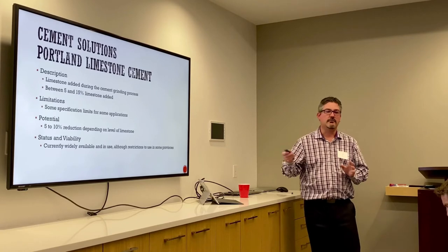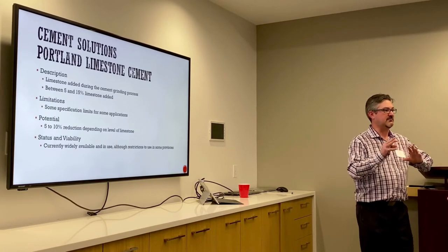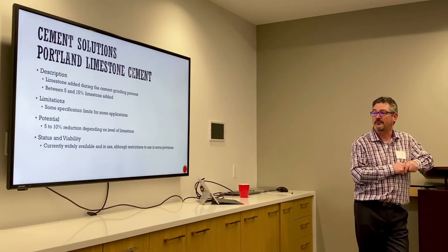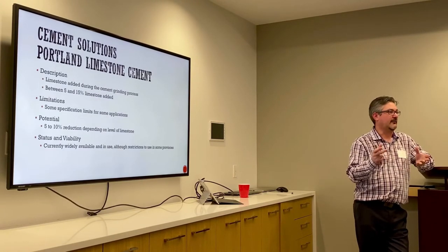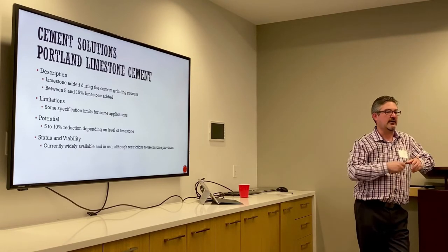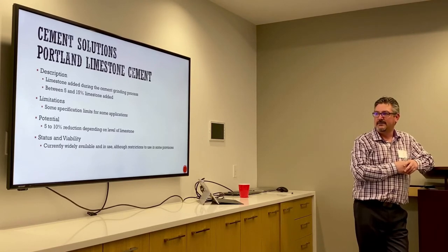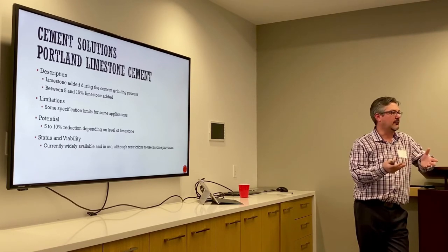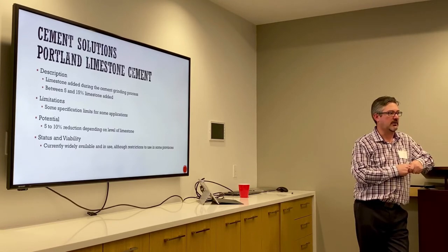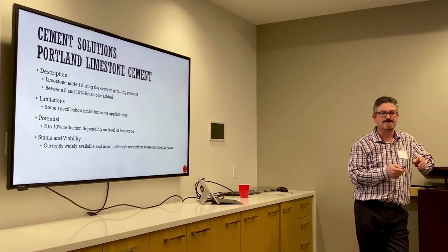So what's the potential for CO2 reduction here? Between 5 and 10%, depending on the level of limestone that's actually used in the cement. And as far as the status and viability goes, for each of these 4 points, I'll be going through all of the different items here and highlighting them. It's currently available and widely used, particularly here in the Lower Mainland. Both cement producers in the Lower Mainland produce a Portland limestone cement.